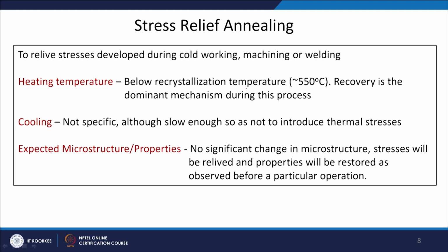It is done below the recrystallization temperature, at around 550 degrees Celsius for plain carbon steel. Recovery is the dominant mechanism during this process. This recovery also we will see when we discuss mechanical properties. Cooling, again, is not specific because we are not doing any phase transformation, although it should be slow enough not to introduce any thermal stresses.